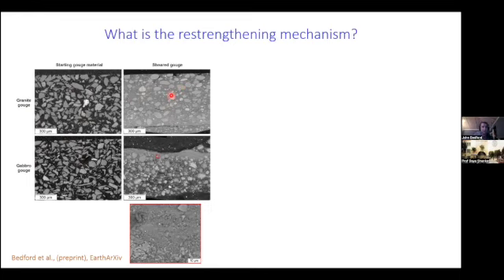You can see that in the granite, the deformation is pretty much distributed throughout the layer, whereas the gabbro fault does show some localization at the tree. And within both layers, we have rounding of large grains surrounded by a much finer grained matrix. There's been a lot of grain size reduction via cataclasis. But although there is a difference in the localization behavior of the two gouges, you might remember the mechanical data for these materials is remarkably similar. So I don't think the localization is having a particularly strong effect here. And in terms of understanding the restrengthening, there's not much we can squeeze out of the microstructures.